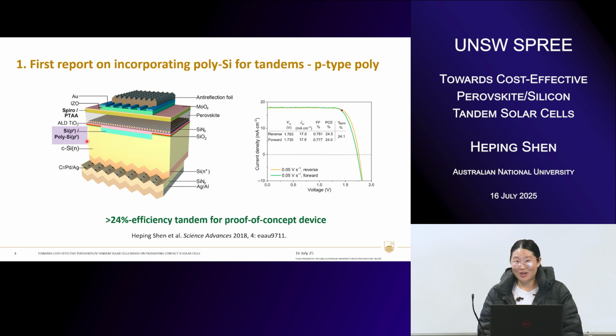Okay, let's look at this structure. I will provide you more details about this structure. As you can see here, this is a cell structure. At the bottom is a silicon solar cell using an N-type wafer as the bulk and also P-type polysilicon as an emitter on the front. At the rear side is a silicon nitride passivation with a localized contact here. And to pair with this cell structure, we use an NIP perovskite solar cell based on titanium oxide electron transport material. So these two cells make a tandem.